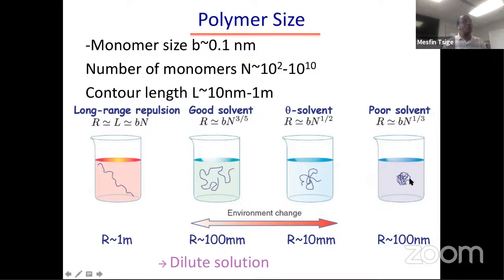If I take this chain and drop it into what we call a poor solvent, that means the polymer doesn't want to be surrounded by solvent. What it does is it goes to a collapsed state. This collapsed state for this longer polymer would be in the order of 100 nanometers. You are in a nanometer scale. If I take this same polymer, but drop it into another type of solvent, where the polymer neither likes it nor hates it, we call it a neutral solvent, then we go from 100 nanometers to 10 millimeters. If we take the same chain and drop it into what we call a good solvent, then it starts to swell, and the size changes to 100 millimeters. Now, this millimeter scale is a length scale that we can actually see.